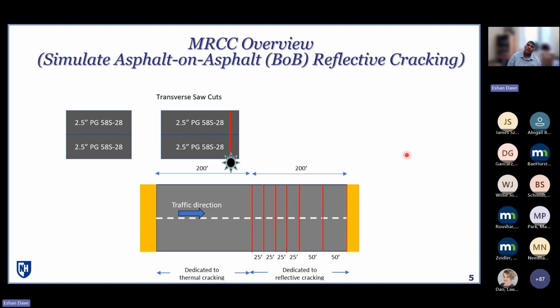Now, in order to really create the most severe reflective cracking conditions, these saw cuts are full depth, as in all 5 inches of the asphalt pavement has been cut all the way to the bottom of that second lift as well. So they really are setting us up with these overlays to make sure they're really getting tortured in a pretty severe way. And that's important because, as with any research study, there's a limited timeline, and we want to make sure that we get to near the end of life of these overlays in a meaningful time frame and don't have to wait 10 or 12 or 15 years to get to it.